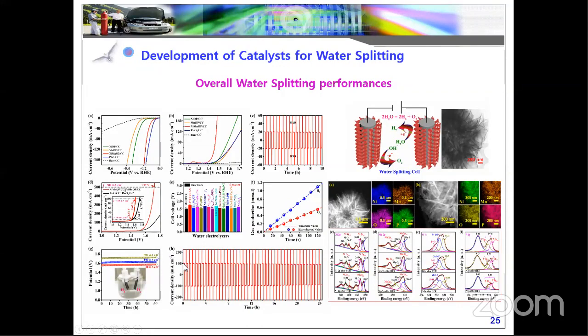And you can see the reversibility for the overall device. The device almost maintained its performance. There is no distortion. So this study, over almost 24 hours, confirms our material has high reversibility. But it is not enough to prove our catalyst is highly stable or active. After these electrochemical performances, we need to confirm by morphological and structural investigations.